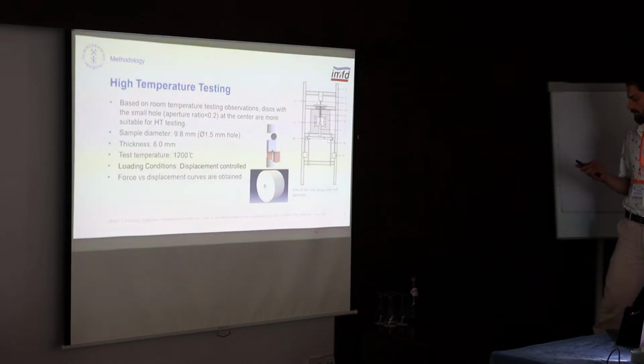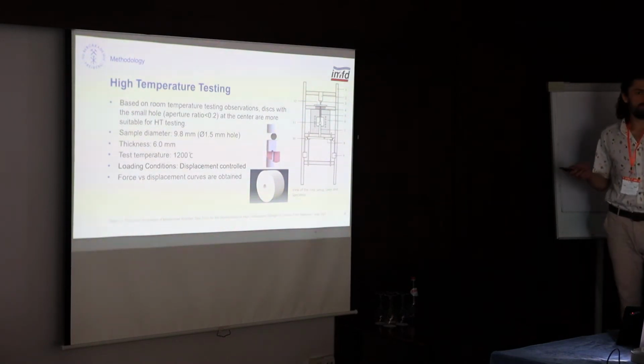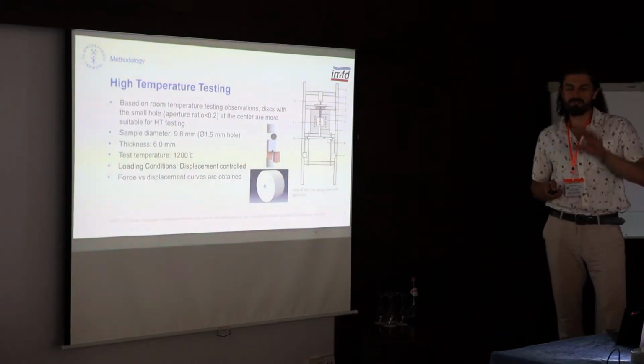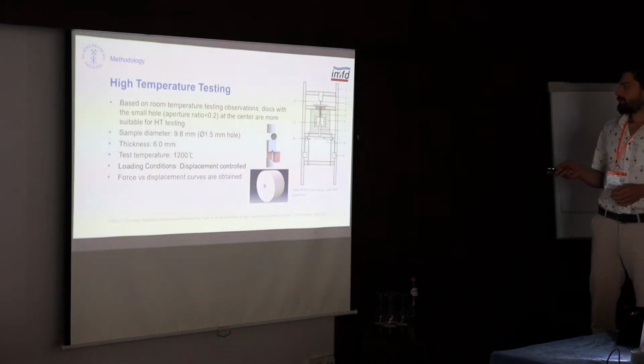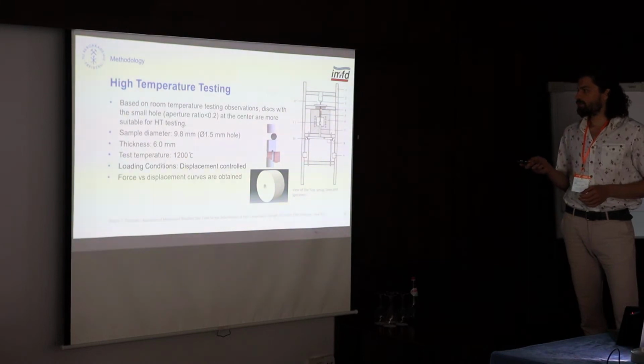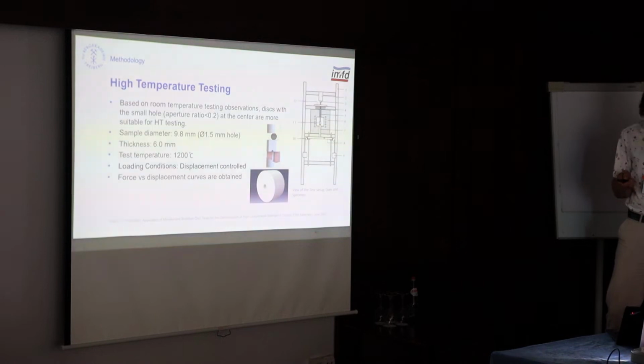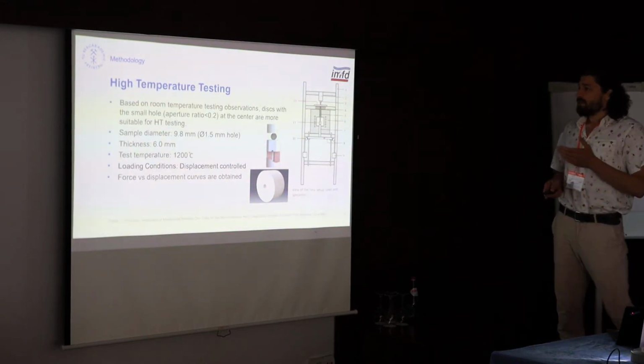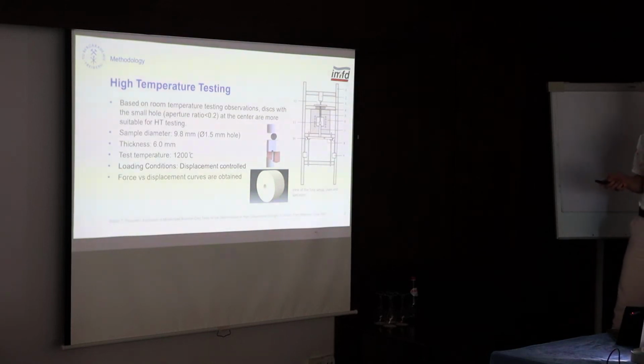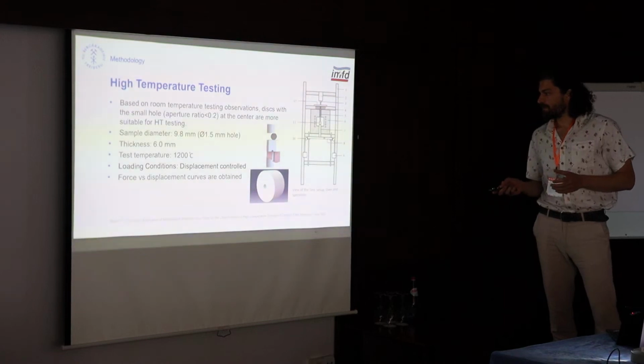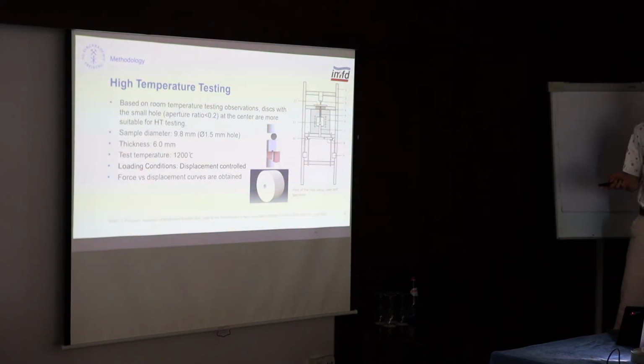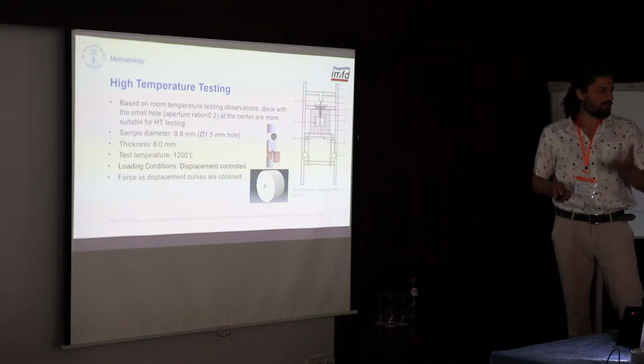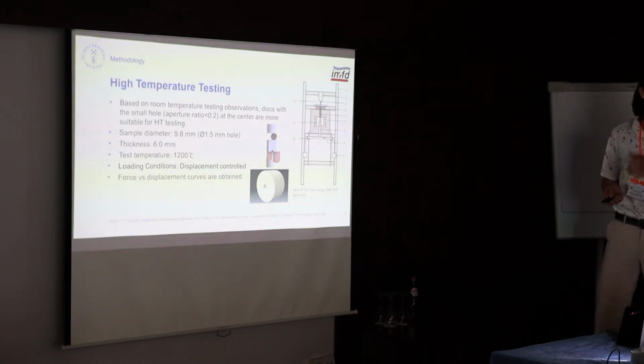So this is my test setup. You can see, first of all, because it's inside the oven, it's closed, so there's no access to the surface of the specimen. And you may also notice that due to the thick isolation layers, I need to use long ceramic parts to be able to apply my forces on the specimen inside the oven. So the takeaway from my previous study was that I need to use the variation with a hole inside, first to decrease the forces that it faces, so therefore I can minimize the displacement of my test setup, the whole thing.